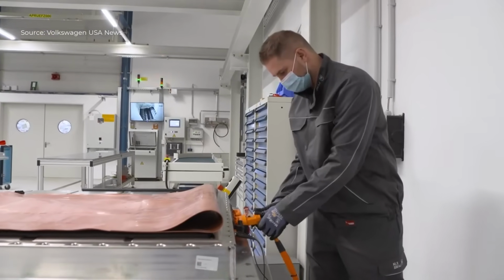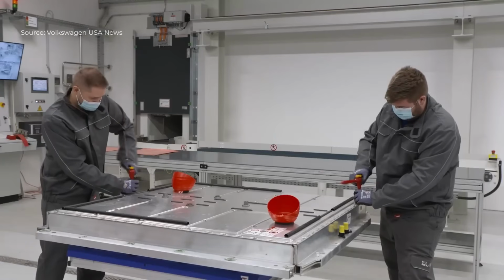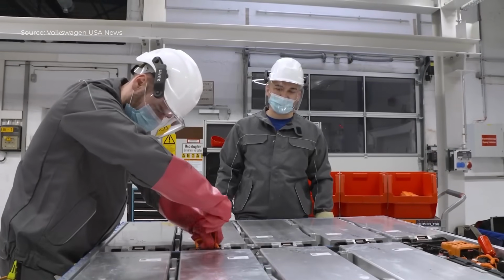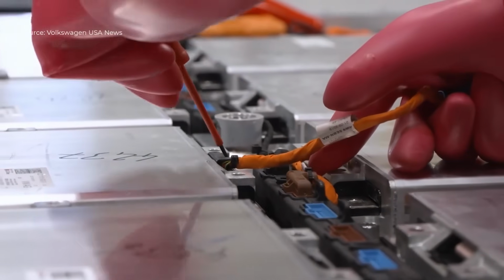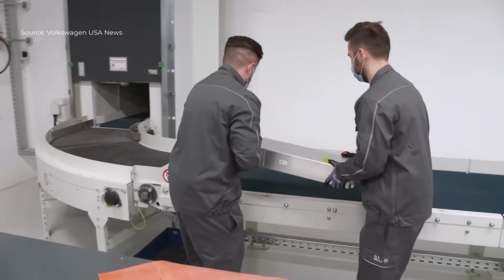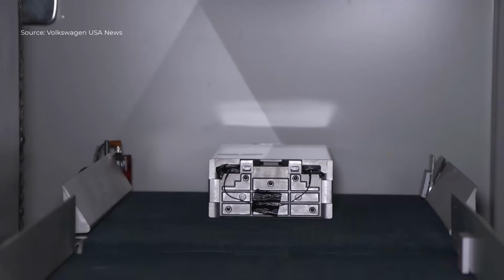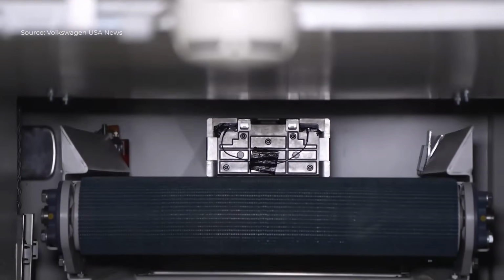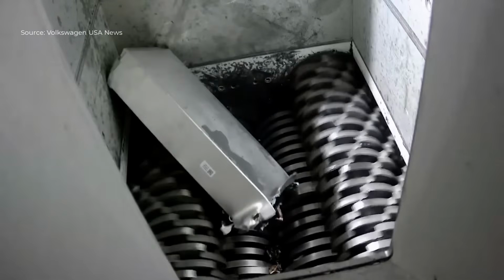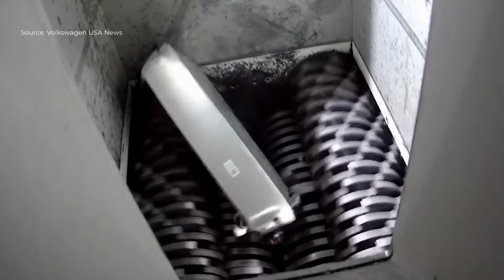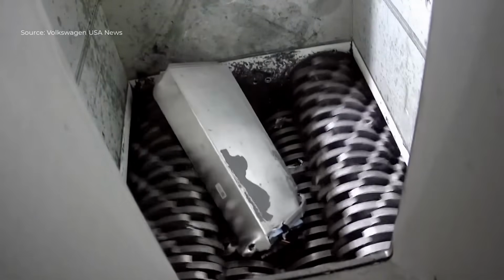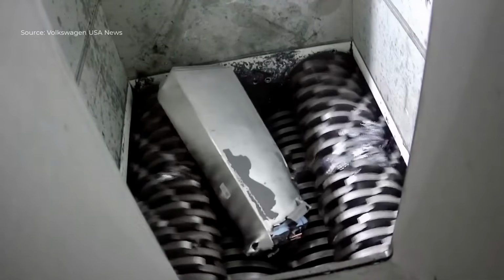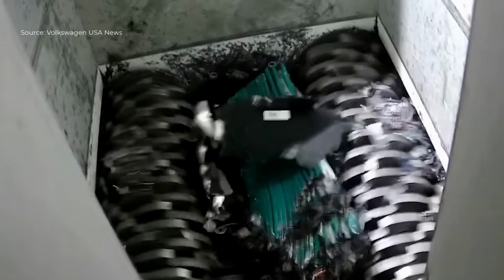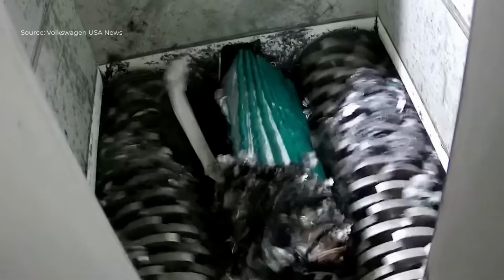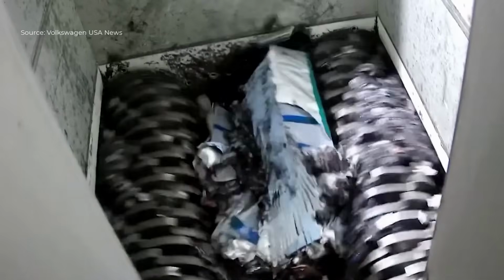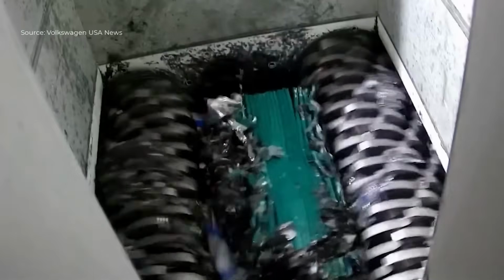Used EV battery packs are first unloaded, tested, and discharged. Functional cells are saved, while the rest are shredded into a damp mass. This mixture is dried and drained of electrolyte, then sifted to extract black powder containing lithium, cobalt, manganese, and graphite. Magnetic and non-magnetic materials are separated, yielding plastic bits, aluminum-copper mix, and valuable metal powder. Volkswagen's process enables up to 95% battery material reuse.